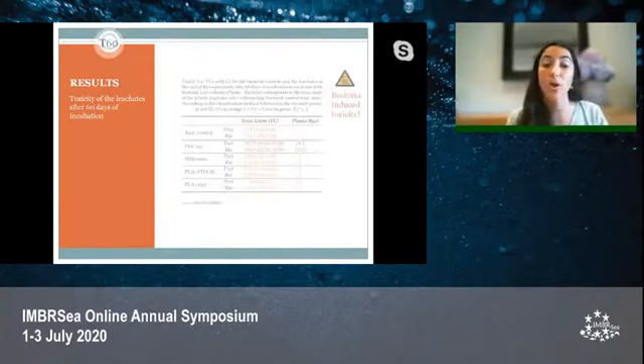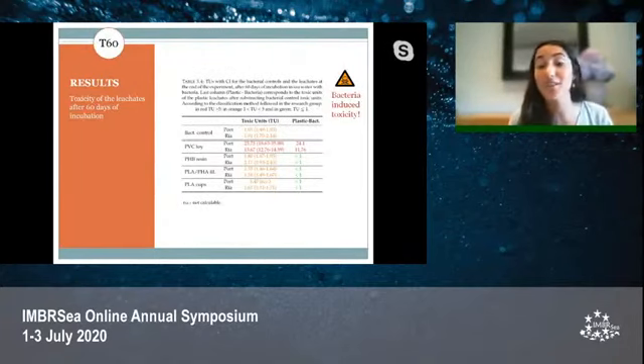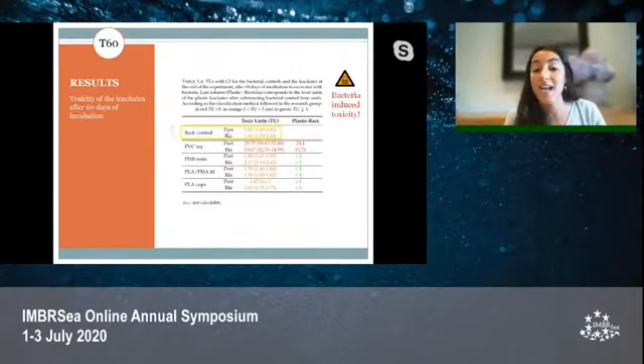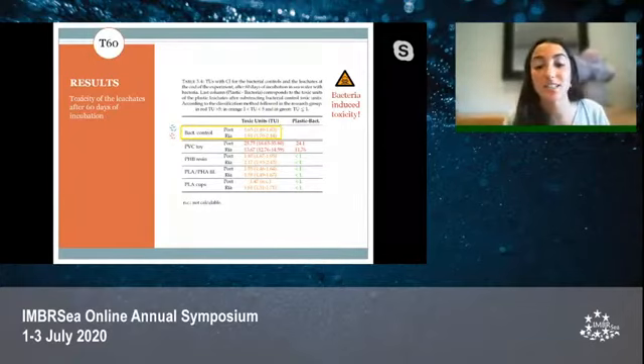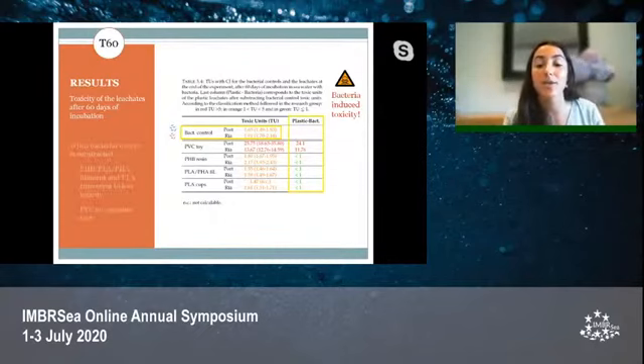And for T60, so after 60 days, again, bacteria-induced toxicity. So what I did was to test dilutions of the bacterial controls in order to be able to get the toxic units. And then I decided to subtract these toxic units due to bacteria from the control in order to obtain an approximate value of toxicity for the plastic leachates. And what I found was that for PHB resin, PLA PHA filament, and PLA caps, actually the toxicity was lost, whereas for PVC toy, it remained being quite toxic.